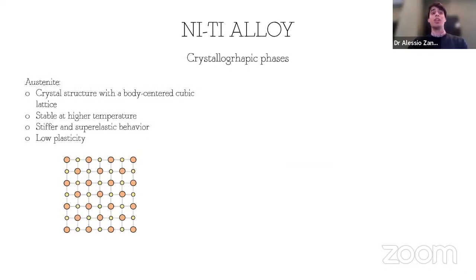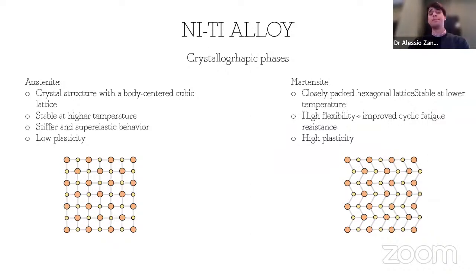Another fundamental characteristic is the possibility to have the NiTi alloy in 2 different crystallographic phases. The austenite, that is stable at high temperature, is formed by this structure. It is stiffer and shows superelastic behavior, whilst martensite has shape memory effect, so a reduced superelastic behavior. It is stable at lower temperature than austenite, but it is flexible and has an improved cyclic fatigue resistance. Between these 2 phases, there is the R phase, that is a sort of hybrid between austenite and martensite. All this information is fundamental to understand why we can use these instruments.